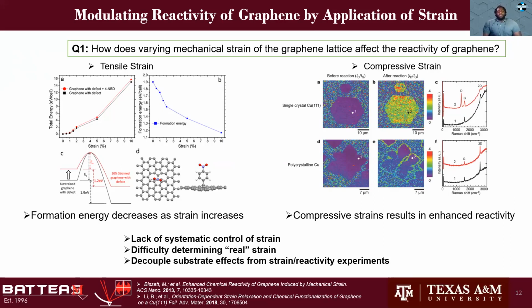And so in our work, we seek to systematically control the strain applied to graphene, and we hypothesize that the true strain that induces an increase in reactivity is actually caused by out-of-plane strain, which mechanically forces graphene to a structure that more so resembles the product state after chemical functionalization.